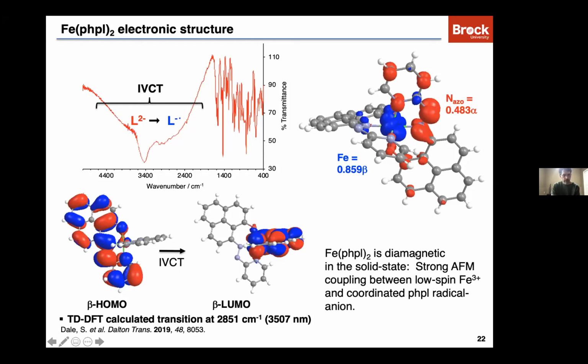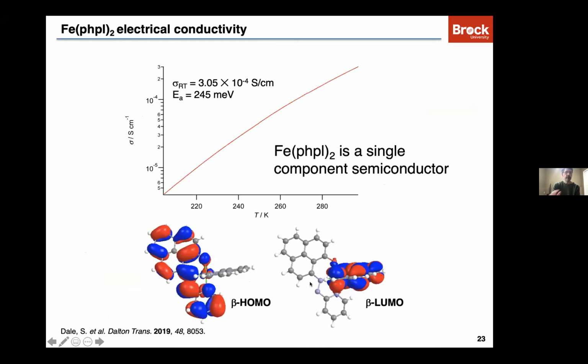However, what's interesting about this complex is that it is a conductor. So we've measured the single crystal conductivity of this complex. For a discrete molecule it actually has relatively high conductivity at room temperature, a semiconductor, and has an activation energy of 245 millielectron volts. So we're currently trying to work out the mechanism behind the conduction. It's not clear, and so we're looking at some band structure calculations currently with this system.